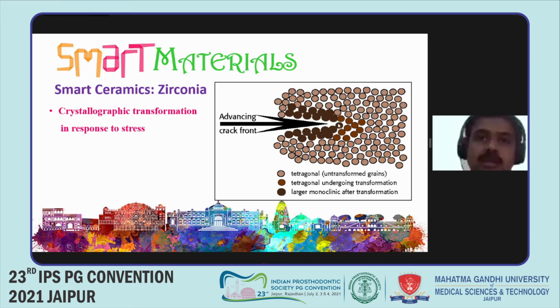So to be very specific, if you look at the advancing crack, all those zirconia crystals, the tetragonal ones which are in the line of that particular crack, start transforming themselves into larger monoclinic. And the other ones which are in the line of the crack also start converting themselves into monoclinic. So therefore, the crack propagation stops at that particular point of time. That's how zirconia behaves. And therefore, you should utilize this particular advantage and see to it that as far as possible, use monolithic zirconia as a monoblock, which is made into all your restorations, because it works out wonders.